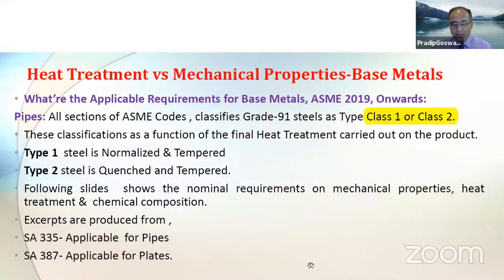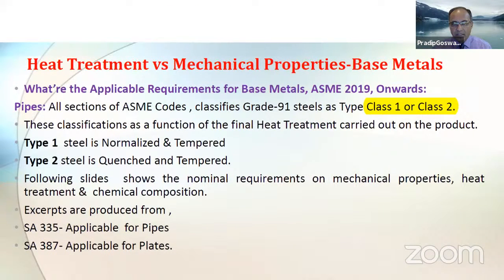Now, from 2019 onwards, all sections of the ASME code classify grade 91 steel as either type 1, class 1 or class 2. This classification is based typically on the final heat treatment. So type 1 steels are typically normalized and tempered. Type 2 steel is quenched and tempered.